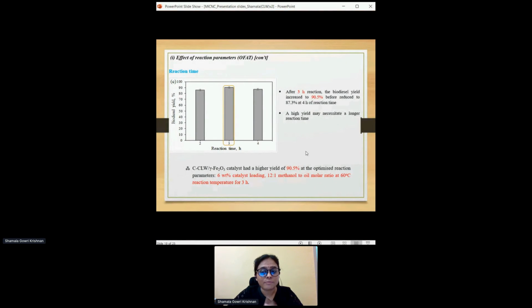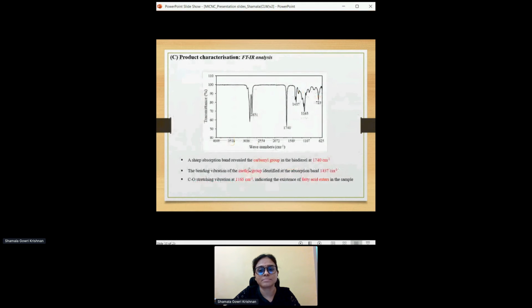90.5%. And with the optimization study by one factor at a time method, we found that this catalyst had a higher yield of 90.5% at optimized conditions of 6 weight% catalyst loading, 12 to 1 methanol to oil molar ratio, and at 60 degrees Celsius for 3 hours of reaction time.